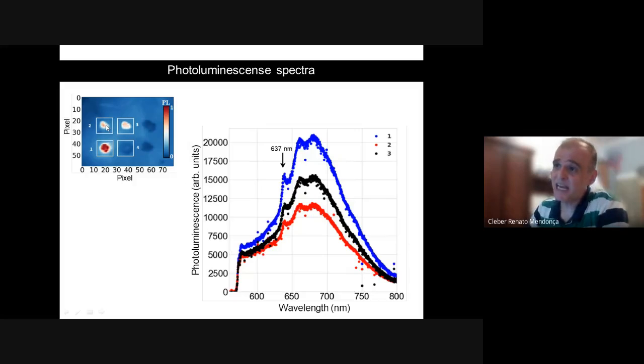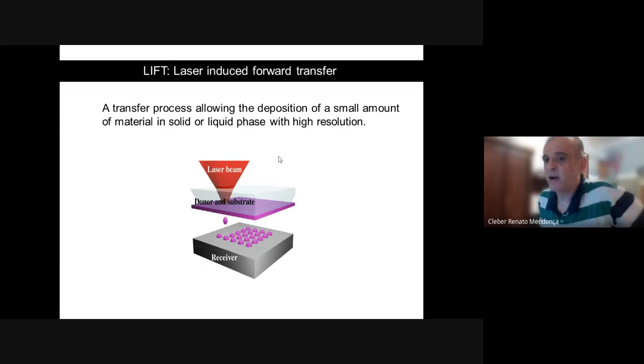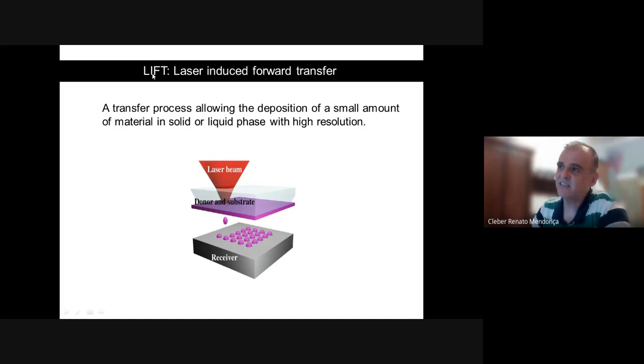And of course, we can measure the fluorescence spectrum just to confirm that we do have the NV center, and that's exactly the signature of the NV center, with this peak at 637 nanometers. So using femtosecond lasers, we are able to fabricate NV centers in localized positions in diamond, and there's a good option for quantum technology.